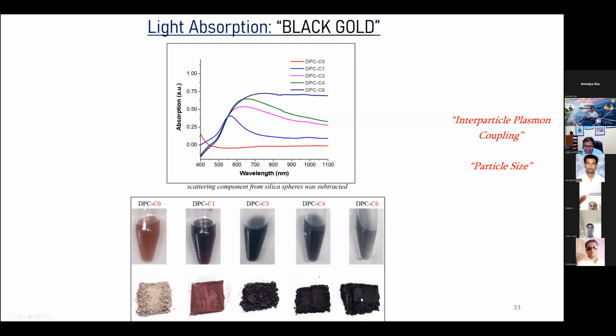Another interesting thing we observe is the gold becomes black. The reason is it is absorbing all the sunlight, so it has to become black. And note, the gold is still metallic. There's no change in the oxidation state, no doping, no hybridization, no functionalization. It's pure metallic gold, but still it is black in color because of interparticle plasmonic coupling and particle size.